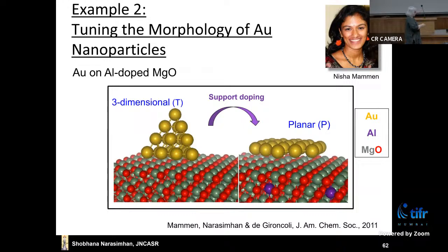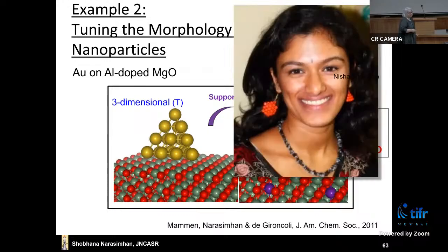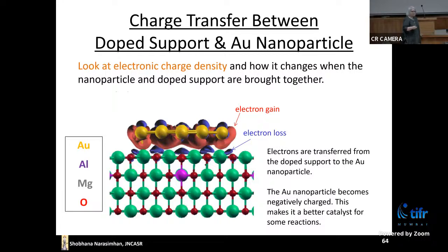And our theoretical idea was that if you do what's called support doping, so in this oxide, these gray atoms are magnesium atoms, and here you replace some of these magnesium atoms with these purple aluminum atoms, then the shape will just naturally change. Okay, and this calculation was done by my student Nisha, and this is a very special picture, because if you've been looking at the picture very carefully, you will notice that her earrings, one of them is the planar nanoparticle and one is the tetrahedral nanoparticle. And why does this change in shape happen? This is again something we can see from our calculations. So what is shown in red and blue here is a gain in electrons is shown in red and a loss in electrons is shown in blue.